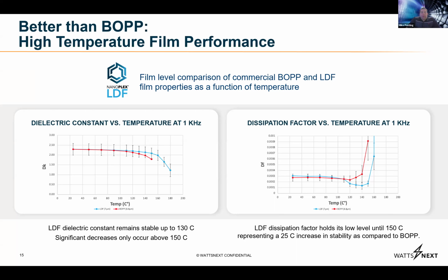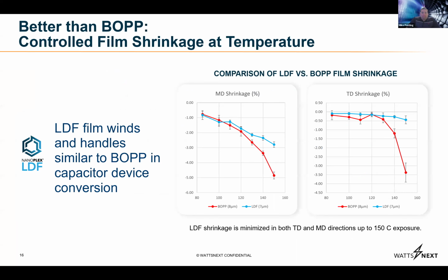And if you look at the graph on the right, the dissipation factor, the losses. So as you're cycling these capacitors, the blue material on the graph, again, the LDF, you see a shift of the data to the right, to the higher temperatures, so you can maintain the low losses well above the ceiling that you get for polypropylene, which is really 120, 125. You start to get significant increase in losses there. We don't see those until you're starting to approach 150C in LDF. So again, it's a thermal reinforcement of the material to maintain property and performance that is vastly improved because of the nanolayering combination of the two different materials. Next slide, please.